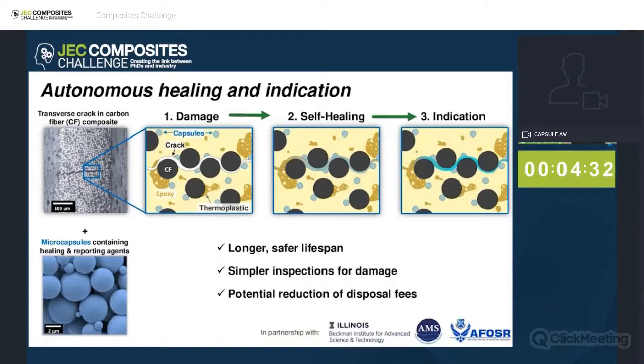This is called fatigue-based failure, which manifests in fiber-reinforced composites as transverse microcracking. These microcracks accumulate over time, causing composites to fail at stresses considerably lower than their static strengths, and is the main reason why structural composites have a limited lifespan. Now, the global composites industry is an estimated $89 billion and growing, and so of course there's an increasing demand